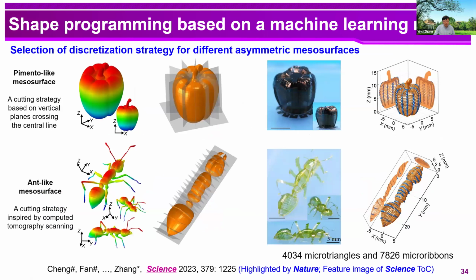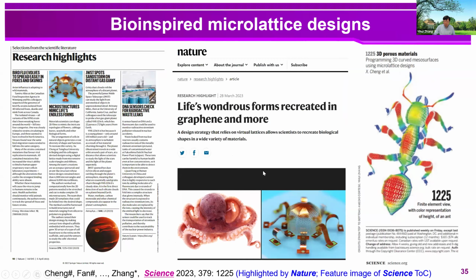And here are two more examples of 3D shape programming based on the machine learning algorithm, including a pimento-like mesosurface and an ant-like mesosurface. And here, by discretizing the ant-like mesosurface with a cutting strategy inspired by CT, we can generate the 2D microlattice design from the machine learning model. As you can see here, we can use around 4,000 micro triangles and around 8,000 micro ribbons to reproduce this ant surface at a millimeter scale. So this pimento-like surface and this ant-like surface were luckily selected by the editors of Nature and Science to highlight in their journals.